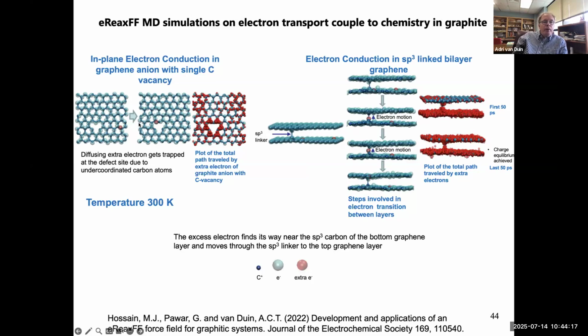But also now we can do more complex things. If we, for example, add a defect, we see that over time, the extra electron actually localizes around the defect, and that's indeed in good agreement with DFT. And if we now look at graphite, and we make an sp3 linker, so we pretty much make a defect in the graphite, very slowly, the electrons can now move across that sp3 linker, and over time, they eventually are now in both layers. But you see, this actually is pretty slow. It primarily moved in the electron-rich layer, but then over time, it can move to the second layer.